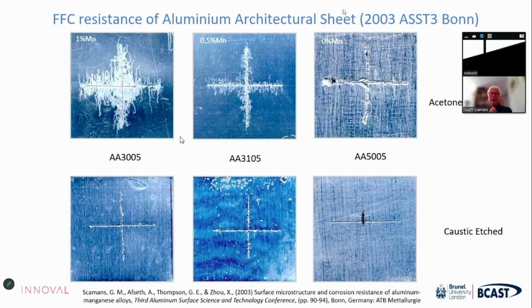And you can see, even with high manganese, if you clean properly and get the deformed layer away, yet again you can't promote filiform corrosion on these surfaces. This work pretty well saved the aluminium architectural sheet market in North America once the ramifications of these understandings were put into practice.